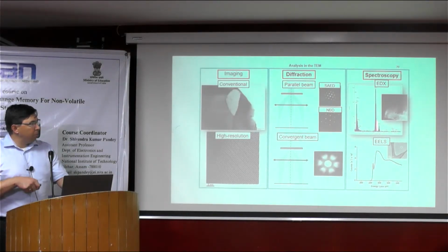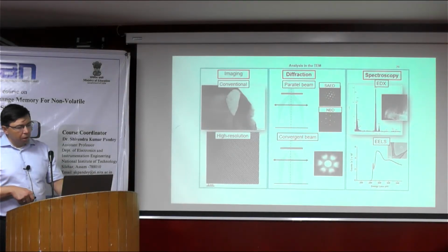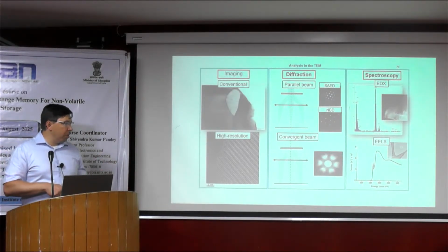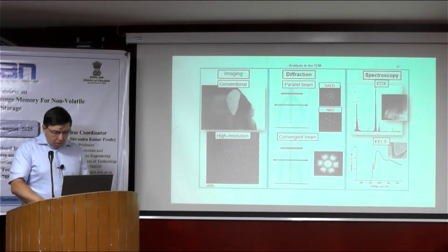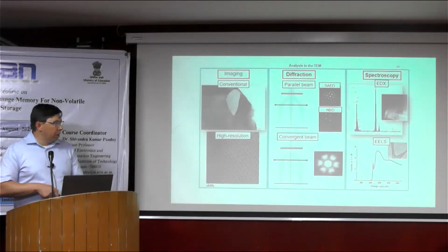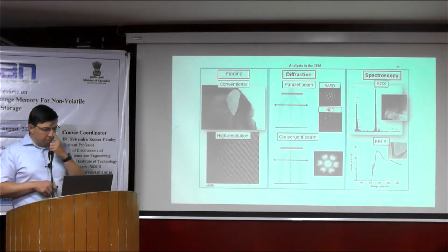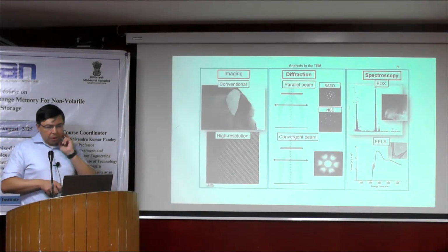So these are both complementary methods in the sense of composition, but from EELS you can study more. You can extract more information like band gap, surface plasmons, composition. Also oxidation states. This is a very famous technique to distinguish between oxidation states in the material.